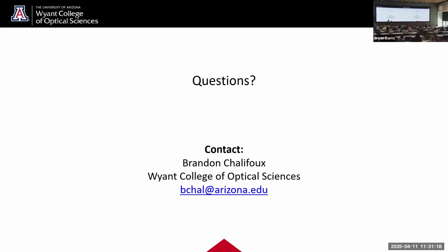Question: What materials have you tested for the laser processing? We have tested a wide range of materials, all glass, with the exception of sapphire. So we've done fused silica and ULE. These work great. ULE also can be slumped at a reasonable temperature. We've also worked with a few other types of glass, but ULE and fused silica are by far the most effective for the ULSF process. For some of the other processes, other types of glass work fine as well. Sapphire also seems to work great for the ULSF process, but is probably less useful for some of the other processes.